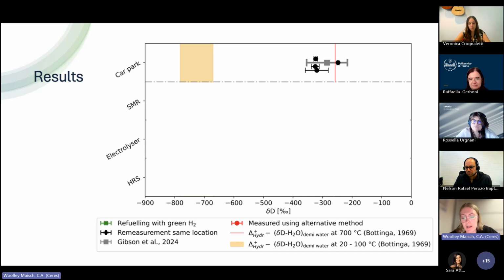So we visited enclosed underground car parks, and we have quite high enhancements of hydrogen there because of the cold start of the engines and the incomplete combustion. We were seeing up to 2 ppm above background in these car parks. And there are literature estimates already from Gibson et al. So in the gray, you can see Gibson et al.'s source signature with the error bars. And you can see that the 4 car parks that we visited are all nicely in line with the error bars, which is a nice sense check. The instrument was off for a while, and now we got it running again, but it's still in line with what the literature suggests it should be.